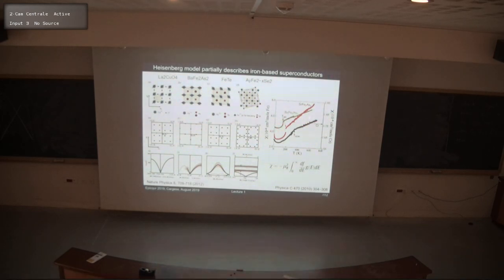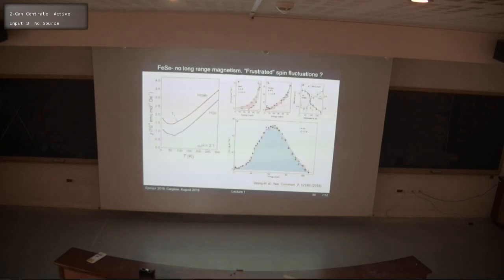And this is the susceptibility of chromium. Chromium is a prototype antiferromagnetic metal, and these materials have very similar susceptibility to what we see in at least this family of iron-based superconductors. So certain things can fit certain materials, but they deviate significantly when the systems become very itinerant.